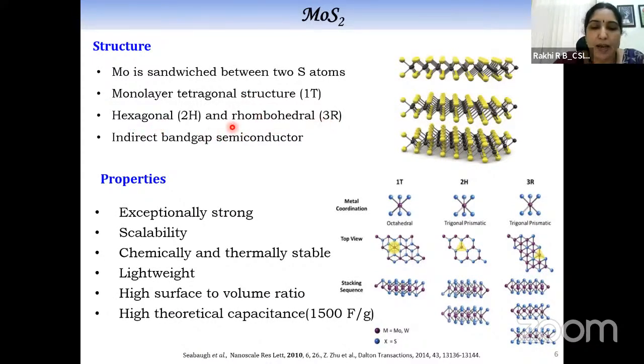rhombohedral structure. When you consider bulk MoS2, it is an indirect band gap semiconductor with a band gap of 1.23 electron volt. And it can be tuned to a direct band gap semiconductor of about 1.9 electron volt by making the monolayer structure, that is 1L MoS2.